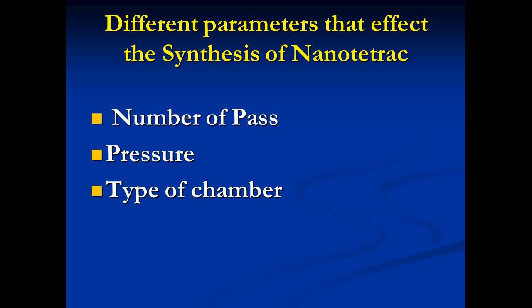Well, we can actually shorten this to 3 passes, but 5 passes gives us the best and reproducible result. So we used those parameters for the synthesis of our nanoformulation in the rest of our formulations.